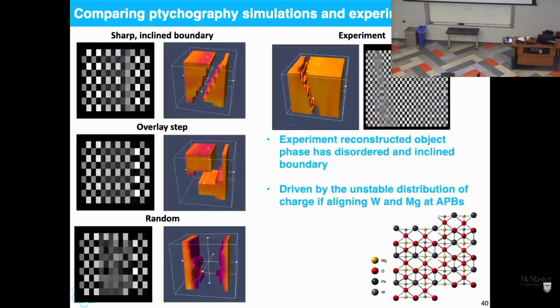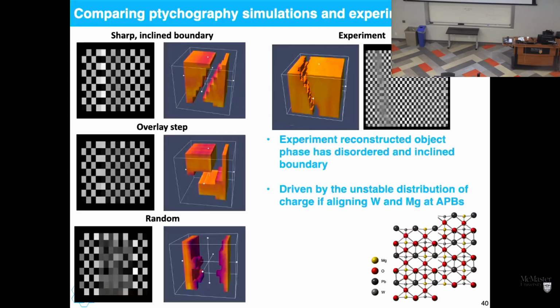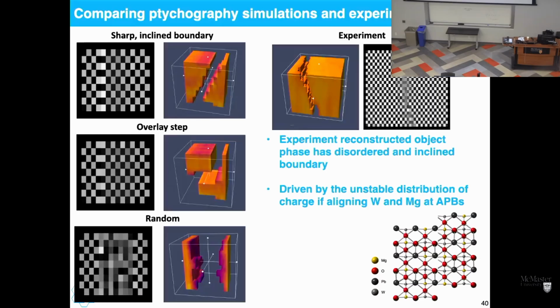So let's just look at the simulations, compare them to our experiment. If we had a sharp inclined boundary, this is what we would see. Very sharp all the way through. Overlay step boundary, and a random site model would just be blurred in the middle basically throughout the entire stack. In our experiment, again, it moves from left to right, meaning it's inclined, and there's some diffuse scattering or some diffuse nature of those components at the boundary, indicating that there's disorder and an inclined boundary that we're seeing.